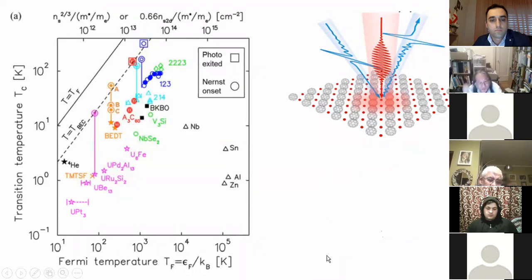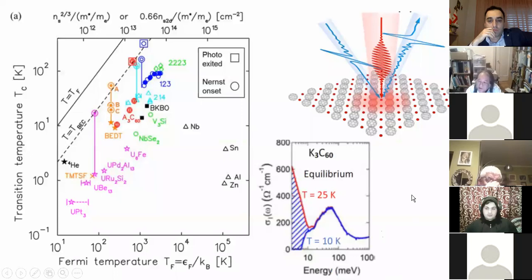An even newer and more interesting effect is that researchers in Hamburg, Germany, about 10 years ago found that if you excite the system by laser, this red one is an infrared laser, that would make an excitation of the superconductors. And then you can measure some optical property by a second laser, the probe pulse, which is shown here by the blue line. What this kind of optical measurement can do is to find something called optical conductivity as a function of the energy of the incident and outgoing light.